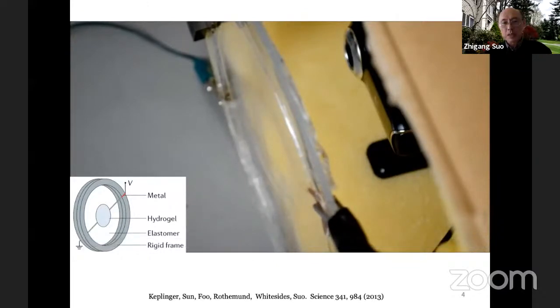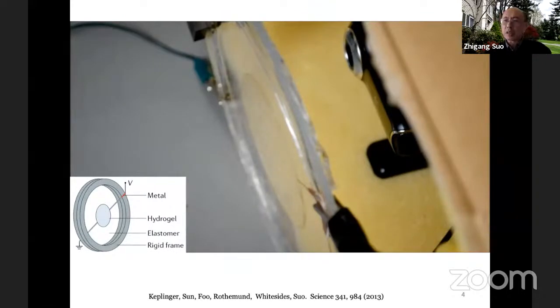As frequency goes higher, the pattern becomes more refined. And the pattern eventually kind of disappeared. The amplitude became too small eventually. But you hear the sound. That small amplitude vibration causes air to vibrate and pass sound to you. So then this is a loudspeaker, right? You apply an electrical signal and it comes out as sound.